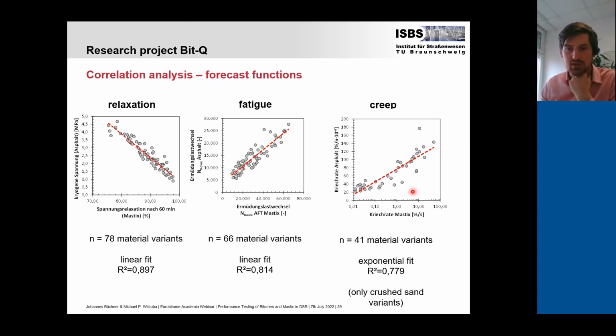And for the high temperature range, here it's not as perfect, but we have to keep in mind this is also a logarithmic scale. So we used an exponential fit here. Regression coefficient was 0.78. And we only included crushed sand variants here. So the ones with natural sand were not used, since we can only forecast with our mastic test the performance of a mixture with crushed sand. Maybe there might be some coefficients to correct this for natural sand, but we are still continuing our work here.